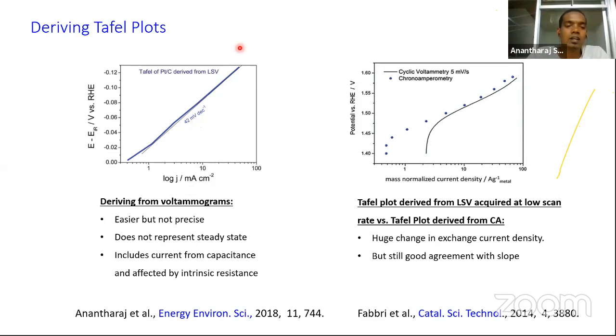So this is a very important application of voltammetry, which can be used to derive Tafel plots. But be reminded that this is not the ideal approach for deriving a Tafel plot, because Tafel plots are actually called, in other terms, steady state polarization curves. But the response we use here from voltammetry is not obtained at steady state. It is obtained by ramping the potential, which does not represent steady state. This difference can cause some false measurement in the actual data, particularly when we are interested in calculating the exchange current density of the electrode under study.